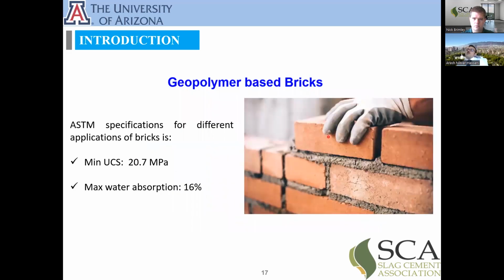If we want to see what numbers we should look at when producing bricks, based on the ASTM specifications, we are talking about a minimum UCS of 21 megapascals in 28 days, and a maximum water absorption of 16%. This means that the bricks we currently produce with the conventional methods meet this requirement. But if we want to produce new bricks using geopolymerization technology, we need to make sure to achieve these goals.